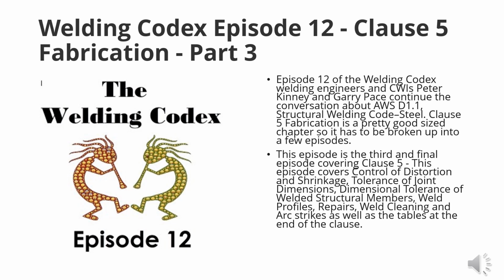What this whole section basically says is, for materials less than 3 inches in thickness, take the root opening. Let's say you have a plate on top of another plate, and one standing up vertical that's going to get fillet welded down to it. Your maximum root opening cannot exceed 3/16. However, it can be 1/16 of an inch and you don't have to do anything. But if it's above 1/16 of an inch up to 3/16 of an inch, you need to increase the fillet. So if we have a 5/16 fillet welding these two plates together and you have a 1/16 inch gap, you don't have to do anything.